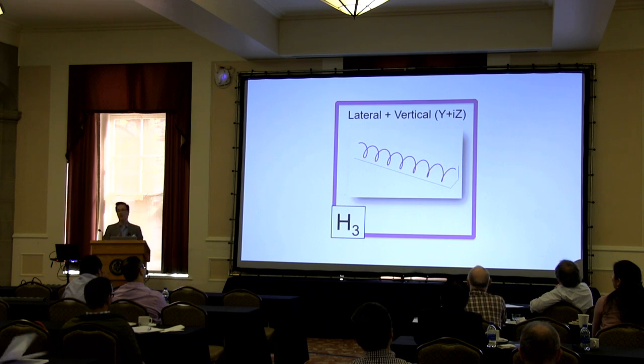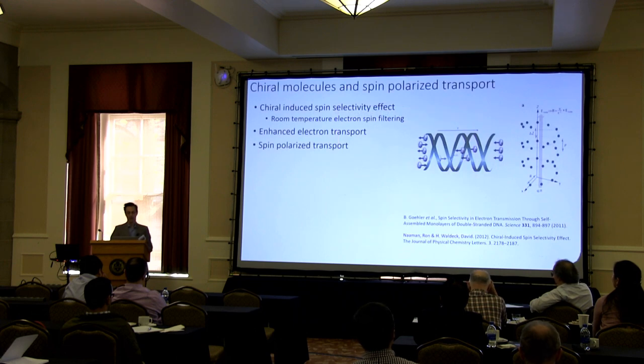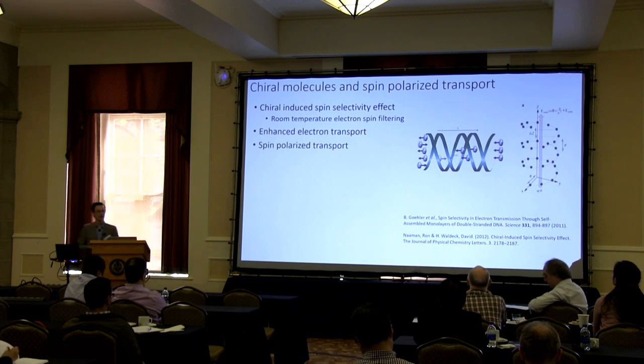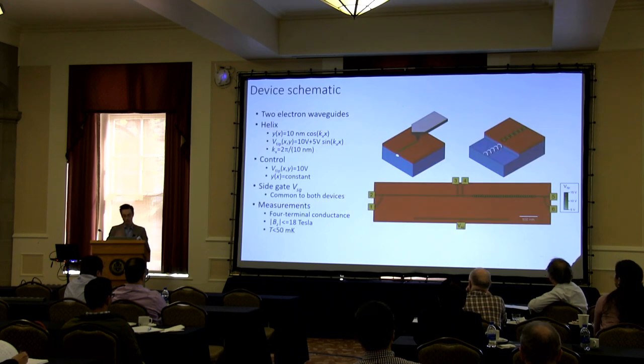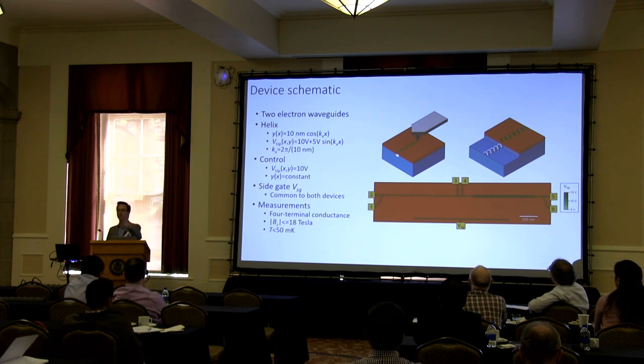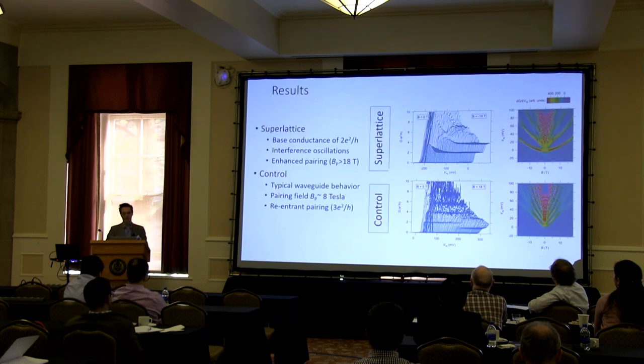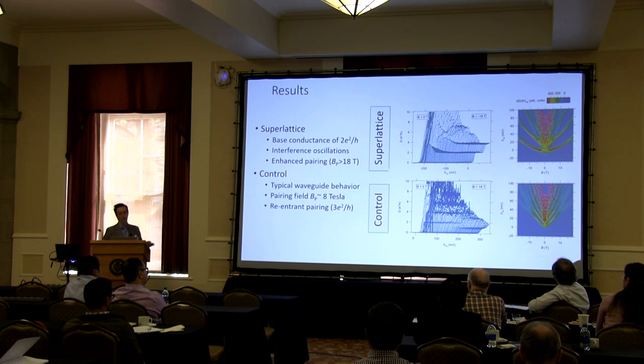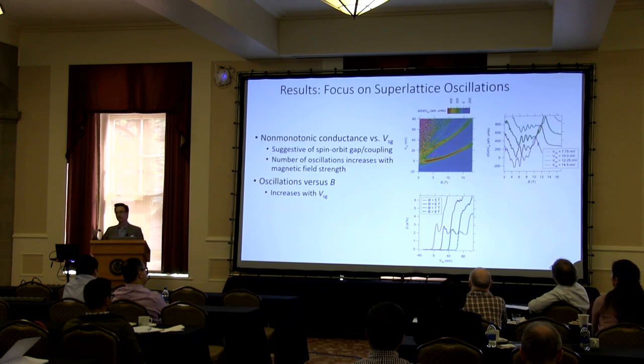So basically, we think we know how to make spiral electron waveguides, and we're inspired by these chiral molecules, which also seem to have a spin selectivity effect that is related to their structure. So basically, what we do is we modulate the lateral position of the wire, and at the same time, we modulate the voltage, but we do it in quadrature. So we believe that this is going to create a spiral shape, and then we're interested in understanding what happens. So what you may see here is basically these sort of ribs in the transconductance that you don't see in a control wire. And these are oscillations that we believe are induced by a spin orbit field